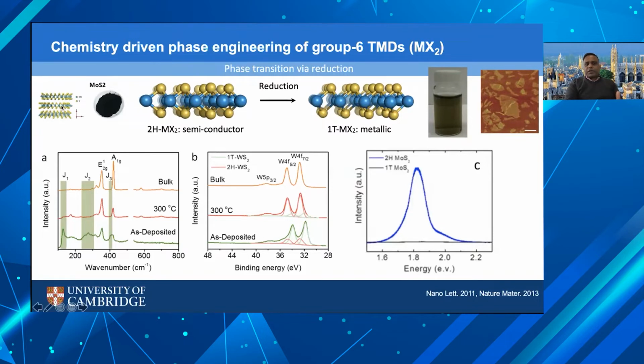And so if you start off with bulk MoS2 powder, bulk MoS2 powder is in the 2H phase, so it's a semiconductor. And it's an indirect bandgap semiconductor because multilayers have an indirect bandgap. But if you exfoliate the MoS2 down to a single layer, then it becomes a direct bandgap semiconductor. However, to do the exfoliation, we use this butyllithium chemistry. That is, we intercalate lithium in between the layers of MoS2, and that chemistry leads to a phase transformation from the 2H phase to the 1T phase.